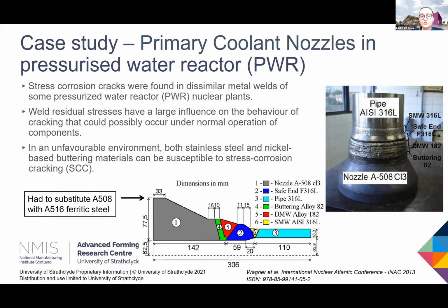And that residual stresses generated in the joint had a large effect on the behavior of these stress corrosion cracks. So as you can see, there is a large amount of alloys present in between the low alloy ferritic steel and the stainless steel. We decided to try and join these both using solid state joining and see what kind of mechanical properties and microstructural effects we can have. Unfortunately, we couldn't get our hands on A508 steel, so we had to go with A516 steel, which we feel still illustrates the general feasibility of the solid state joint.